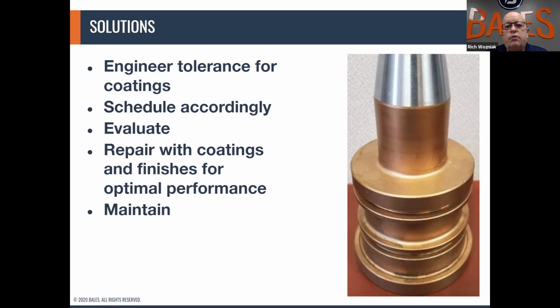Schedule accordingly, especially on new tool builds. It's important that you schedule your jobs so that you can calculate in the plating time, which is typically 7 days for a nickel product and about 15 to 20 for a chrome product. Just some things to think about.